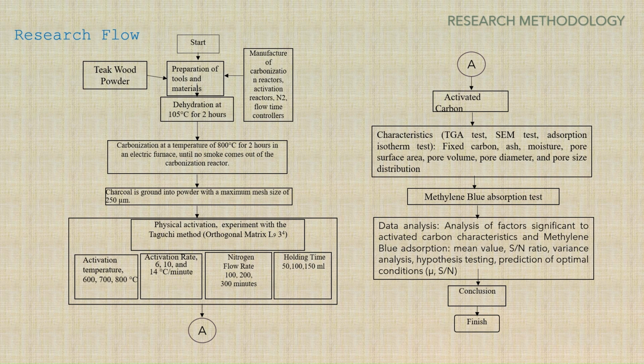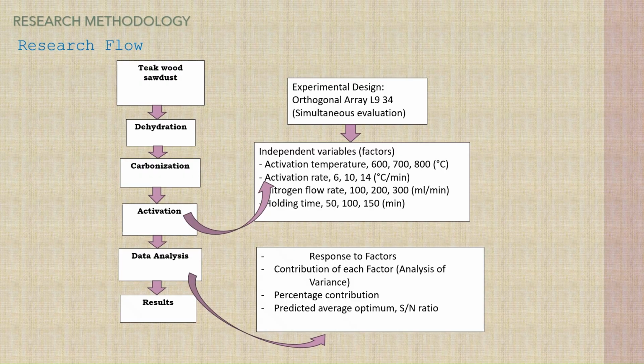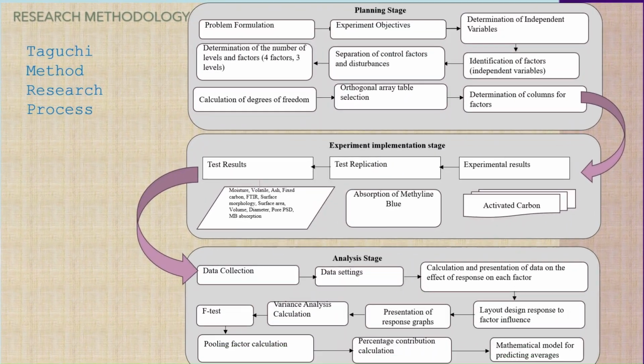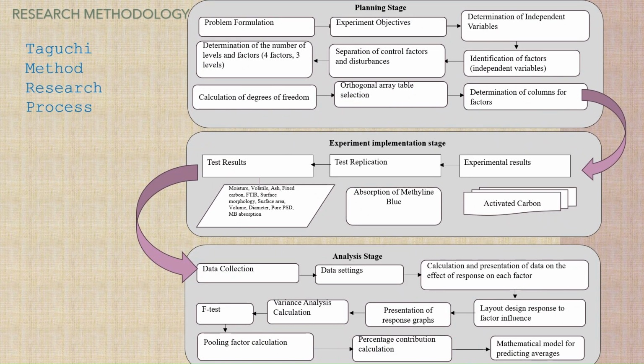The teak wood sawdust is dehydrated at 105 degrees Celsius for 2 hours to remove moisture prior to carbonization and activation. After carbonization, samples undergo activation based on Taguchi design parameters, followed by comprehensive material characterization. All specimens follow the L9 Taguchi matrix, ensuring the systematic evaluation of activation parameters and efficient optimization.